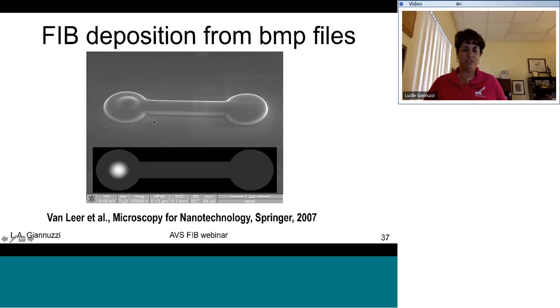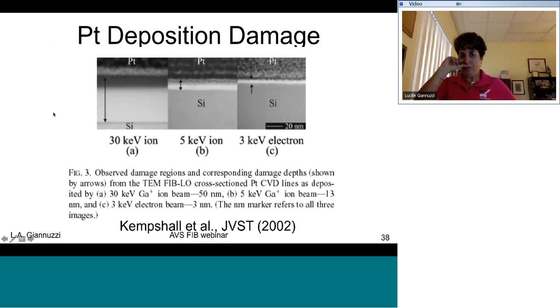So here is an example of this. This is what the bitmap file looks like, and this is what the subsequent deposition looks like. The one thing that you should be aware of is that deposition can cause damage because on the onset of deposition, you still have the interaction of that energetic ion with your sample surface. And you've got that onset of competition between deposition and milling.